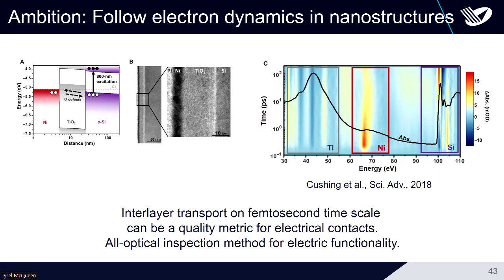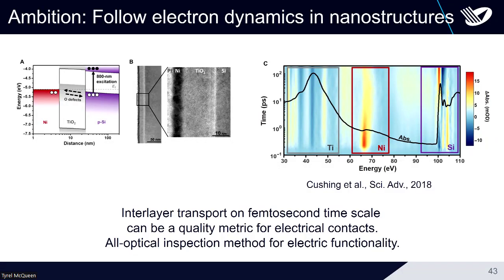It's a very nice paper here from a former colleague of mine who simply made a junction out of 3 materials, nickel, titanium oxide, and silicon, photo-excited that, and then he could follow what is actually happening in the individual layers as a function of time, because we know in the X-ray range that different atoms always absorb at the same energies, because these are inner valence absorptions that we're doing, so they're not much affected by chemical bonding. It's the reason why we use synchrotrons for all kind of X-ray absorption spectroscopy.